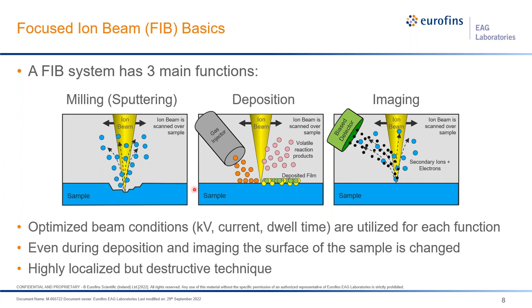So in the case of deposition, we use a precursor gas introduced via a needle close to the area we're working, and there are many different precursor gases. The incident ion beam then decomposes this gas, and we deposit material out of that gas. And so typical deposition films are like platinum, tungsten, or carbon. These are most commonly used for sample preparation.